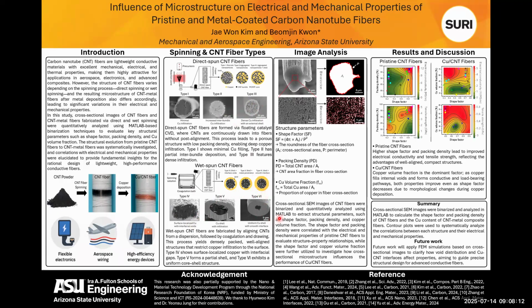To analyze this structure, we used cross-section images of CNT and copper CNT fibers, which were binarized and processed using MATLAB. From these images, we extracted three key structural parameters. The first is the shape factor, which indicates how circular the fiber cross-section is. The second is packing density, which reflects how densely CNT fills the cross-section. The third is copper volume fraction, which measures the proportion of the area occupied by copper in the composite fiber.